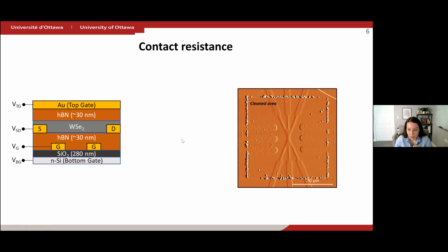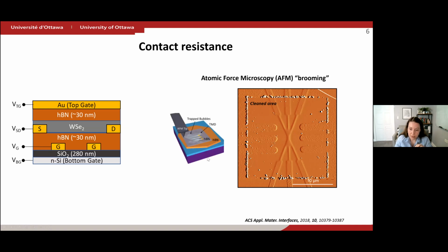Another important development that we've been discovering as it relates to contact resistance specifically is this device that I've shown you before in the context of making quantum dots. These are the local gates. There is a 2D material and there's these contacts on top. This is an atomic force microscopy image. And we followed this paper that describes how you can use an AFM tip to clean residues off 2D materials. These residues come from the nanofab process. They're typically polymers that you've used for the lithography. And so indeed, we control the parameters of the contact between an AFM tip and the surface to really move, and we call it nano brooming, to move to the side these contaminants, leaving behind a very good surface. And so it's this technique that allowed us to have good electrical contact between the source and the drain and the 2D material to be able to create quantum dots.